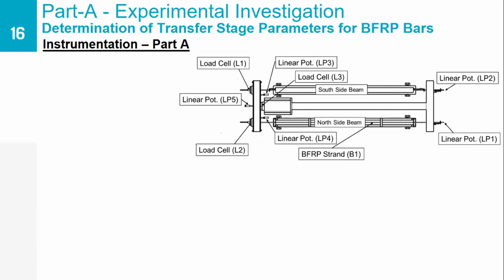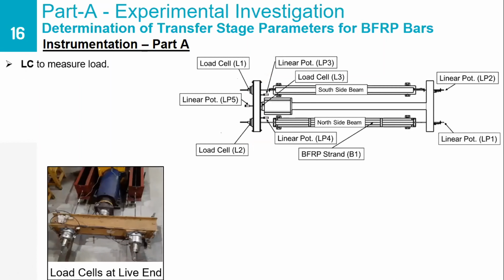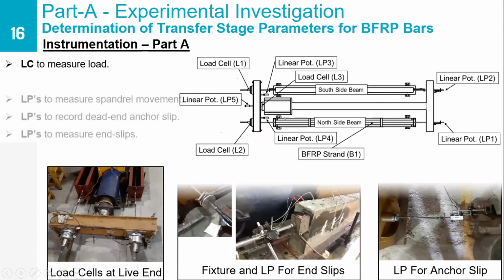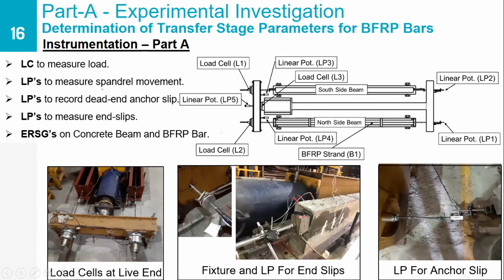So now we'll talk about the various types of instrumentation that we have used in this test setup. So we have used linear potentiometers. We have also used the load cells for measuring the pre-tensioning load that we are applying on the BFRP bars. We have used linear potentiometers to measure the movement of the spandrel beam on which we apply the load to pre-stress the prestressing bars. And we also used linear potentiometers to record the end slips between the bar and the anchors, as well as the bar and the concrete. And also strain gauges have been used on the concrete beam and the BFRP bars to measure the strains after the release of the prestressing force.